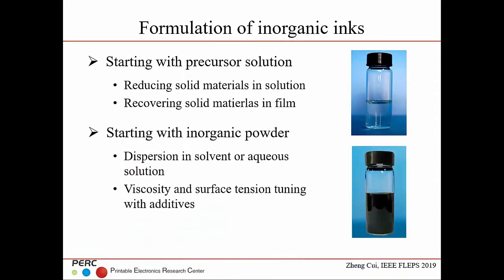And there's another way, which is simply to start with the powder, and you disperse the powder into solvent or aqueous solution, and you use additives to change the viscosity and surface tension, then you get the ink. So, for example, this is the silver ink. This one starts with the precursor solution, so it's transparent. You can't see any solid material. But this one is made by dispersion, where all the particles inside the solution make it not transparent.